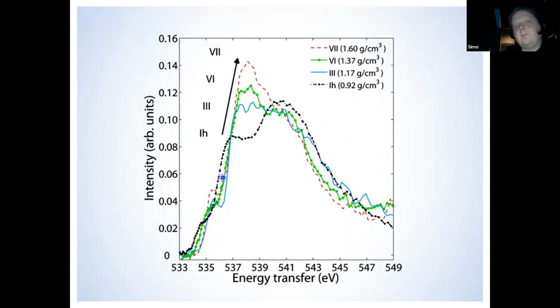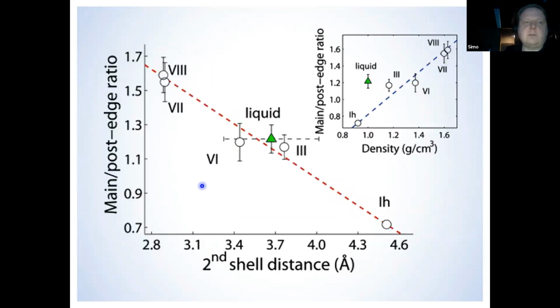So then one can quantify the spectra in many different ways, and we did density functional theory calculations and many other things. But a very simple thing is to take the pre-edge to main edge intensity ratio after fitting the spectra with Gaussians, and then plot that as a function of density. Sorry, it was the main to post-edge ratio. And one can see that it follows kind of this line, except that liquid water is an outlier in this plot.